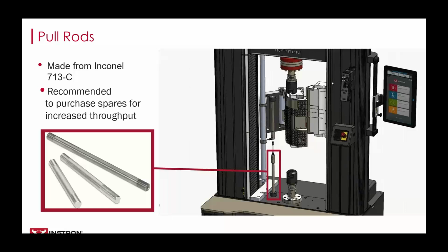Moving on to pull rods, you can see on the right, we have a visual for how the load string begins to be assembled. I'd like to recommend adding anti-seize grease or lubricant to the ends of the specimens to prevent the chance of your specimen accidentally welding to the holder if you're using a threaded connection. The load string configuration typically consists of pull rods made from a high temperature resilient material, such as Inconel 713C, which has a relatively low thermal expansion.